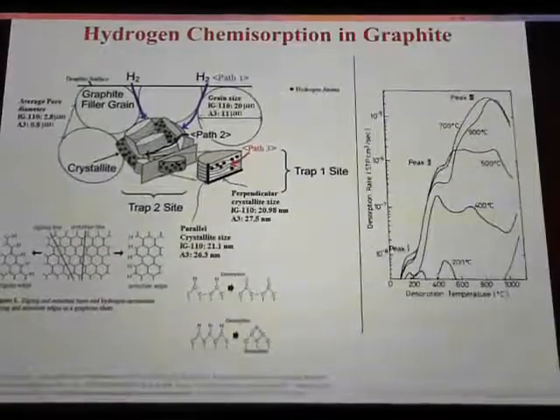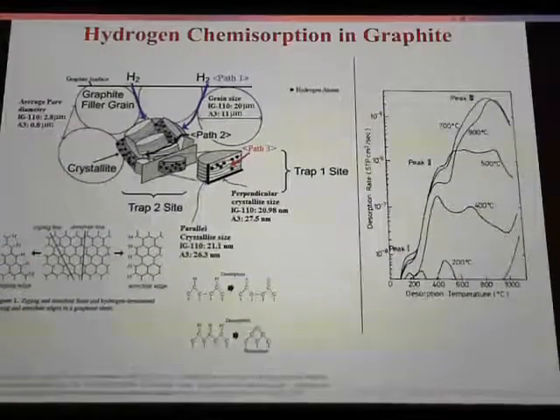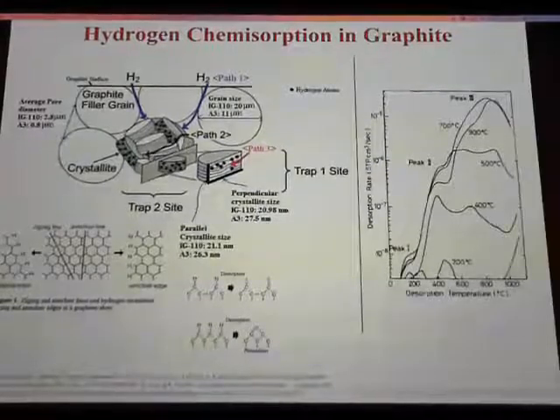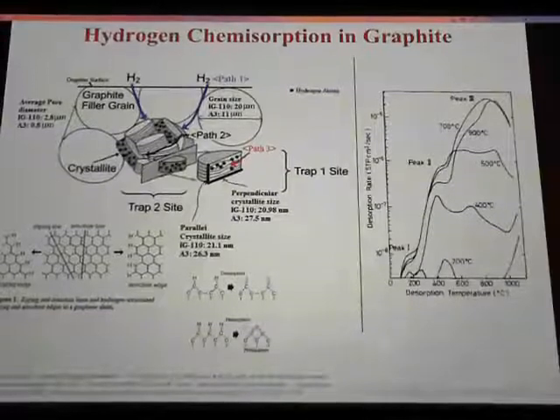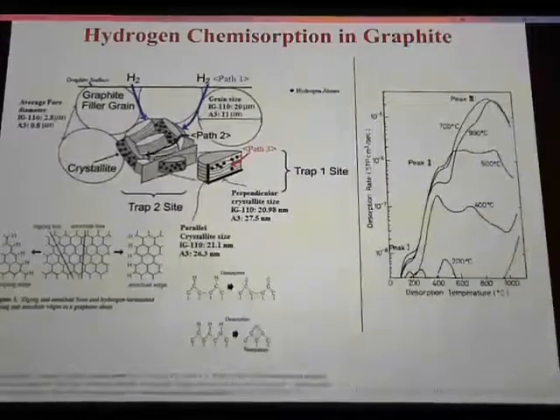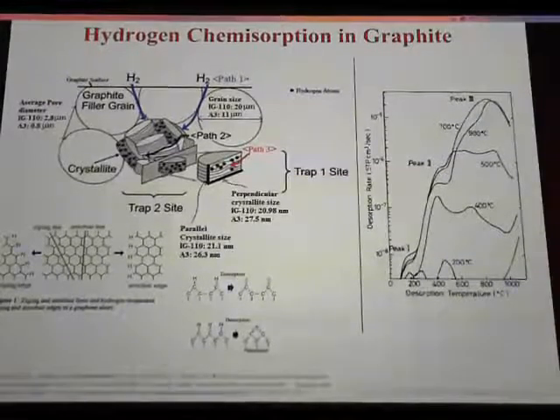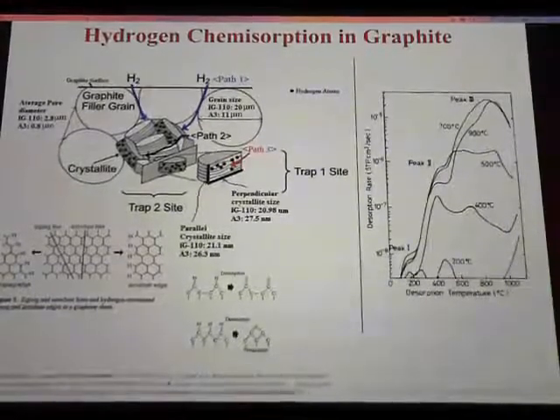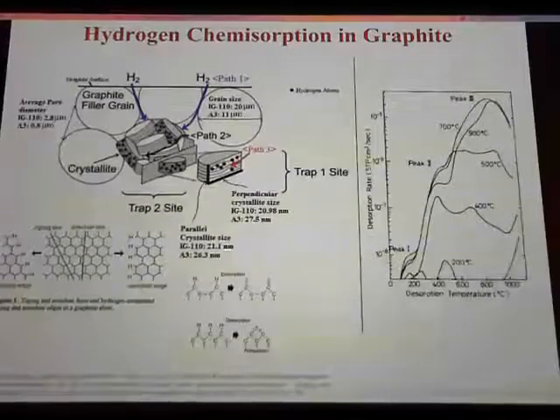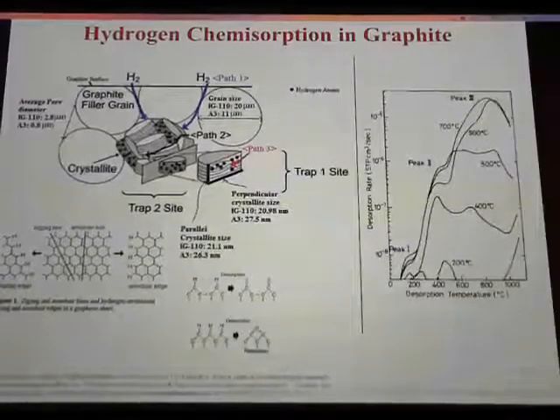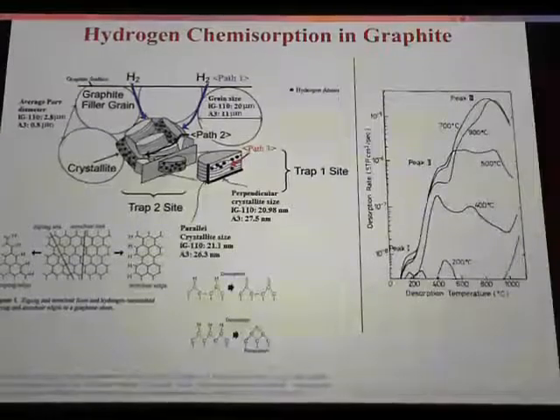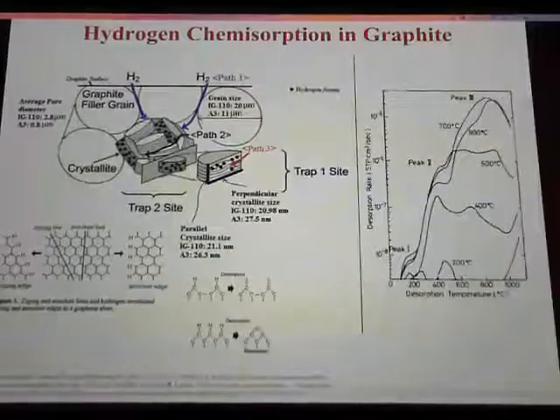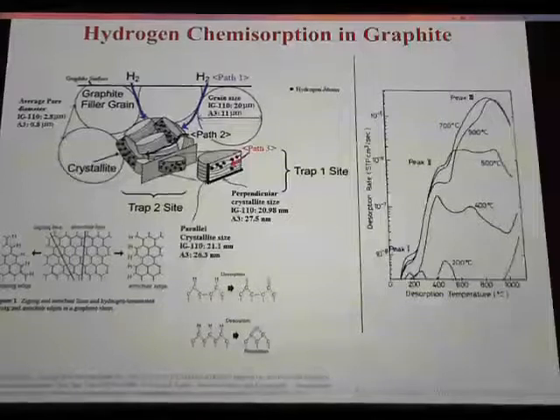It's more dense at the surface, and the graphite experts tell me that it has to do with how they impregnate it to increase the density, and so it's probably not the lower density at the surface that is explaining that, but we're still doing that study, so don't take my word for it yet. But there's another reason that that profile might look different, which is that when hydrogen and tritium transport within graphite, it bonds chemically to the graphite. And so what you have is not just a diffusion process, but you have a trapping and detrapping process.